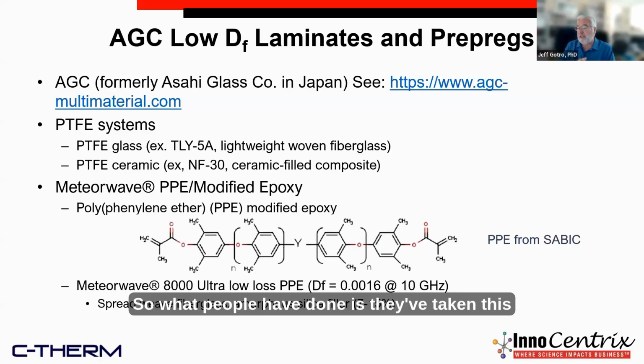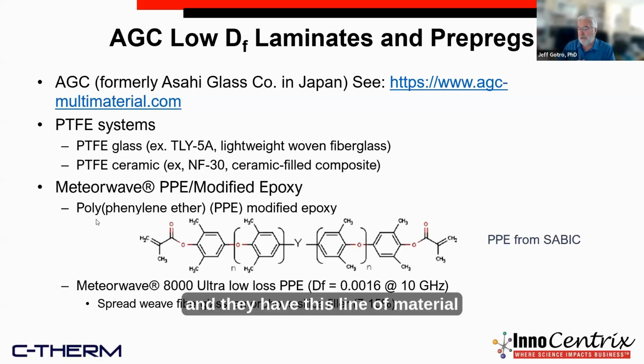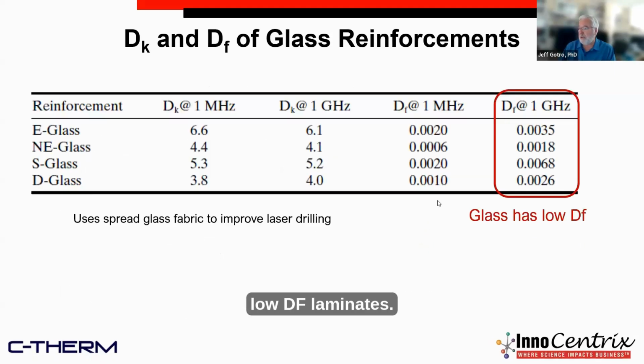So what people have done is AGC, Asahi Glass Company, has formed these modified epoxies, and they have this line of material called Meteorwave, and they have very, very low dissipation factor, and they have relatively good dielectric constant as well. So these are used to make these very low DF laminates.